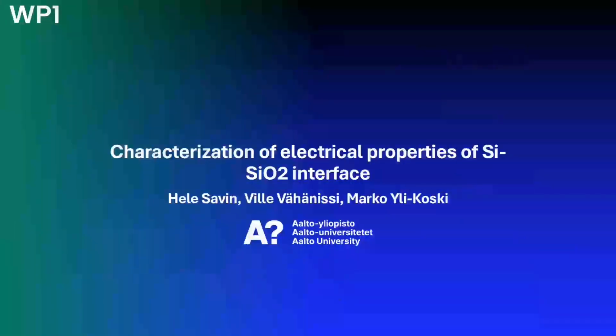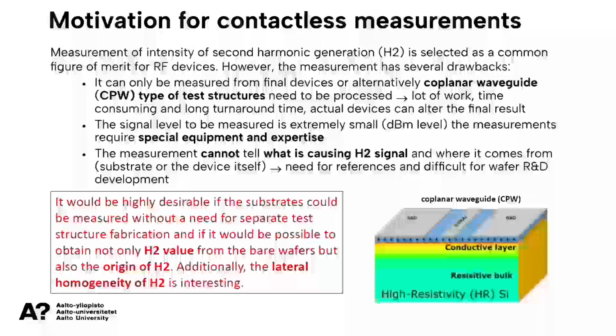First, let's look at what Aalto has been developing on the characterization part. Their goal is to measure directly from the wafer, not touching it in any way, the harmonic generation properties. Traditionally, it's done by fabricating RF devices like coplanar waveguide structures on the wafer, measuring them and then extracting the harmonic generation properties from the results. That's indirect, doesn't distinguish what the origin of the harmonic signal is, and of course destroys the wafer as such. So is it possible to make a non-contact mapping of the wafer properties for process wafers and have this characterized as an inline measurement?